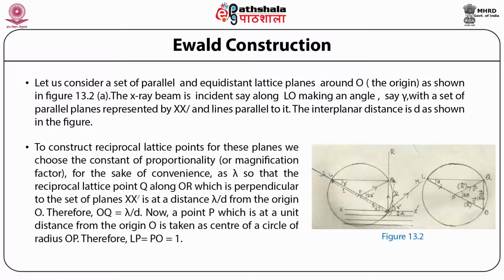To construct reciprocal lattice points for these planes, we choose the constant of proportionality, or what is called the magnification factor, for the sake of convenience as lambda, so that the reciprocal lattice point Q along OR, which is perpendicular to the set of planes XX prime, is at a distance lambda by d from the origin O. Therefore, OQ is equal to lambda by small d. Now a point capital P, which is at a unit distance from the origin O, is taken as the center of a circle of radius OP. Therefore, LP is equal to PO is equal to 1.